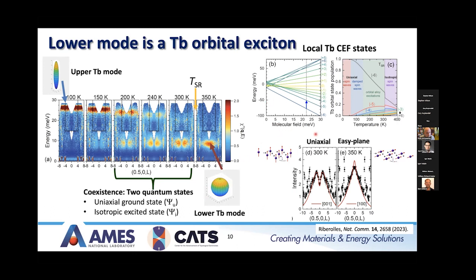On the right side here, I just show some more details of the crystal field states. Basically, the molecular field, of course, is going to also split the terbium crystal field states. And then this nice graph here shows how, when warming up, you get this coexistence of the uniaxial and the excited isotropic states. And then once you're above the spin reorientation transition, all that remains is the isotropic. We have some proof of that that's discussed in the paper here.